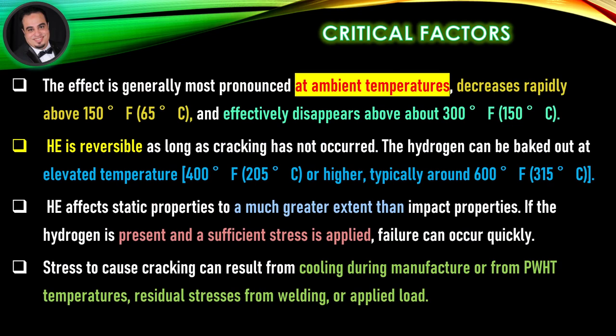The effect is generally most pronounced at ambient temperatures, decreases rapidly above 150°F, and effectively disappears above about 300°F. Hydrogen embrittlement is reversible as long as cracking has not occurred. The hydrogen can be baked out at elevated temperatures — 400°F or higher, typically around 600°F.